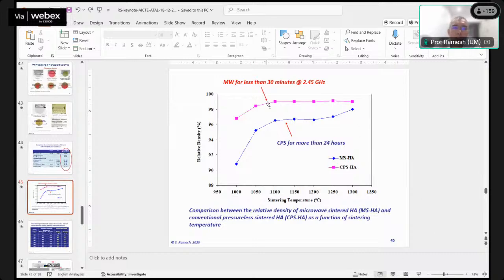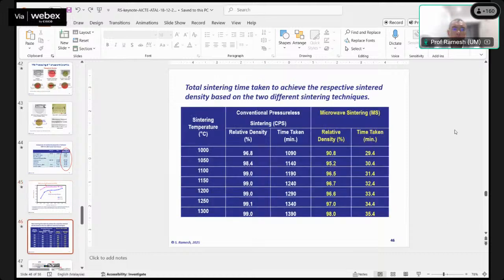So just to compare, microwave sintering at 30 minutes at 2.45 gigahertz, as you can see, as compared to conventional sintering at different temperatures, is much better in terms of densification. Conventional is done for 24 hours, microwave is done for 30 minutes at the same temperature. So you can see the improvement there in terms of densification. This just shows the similar thing in a table form.